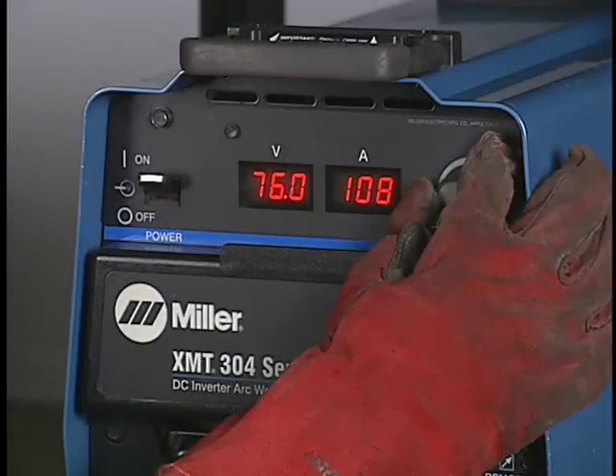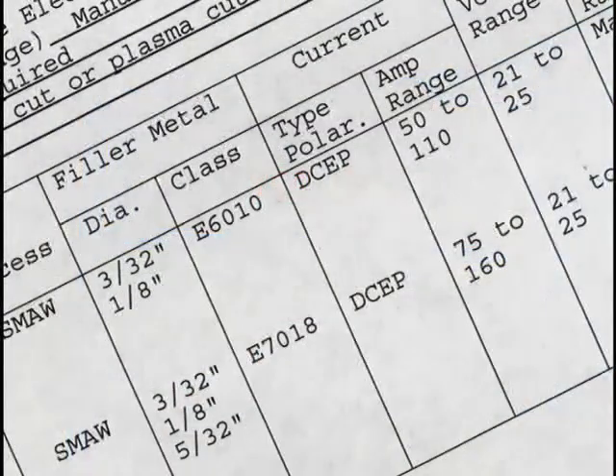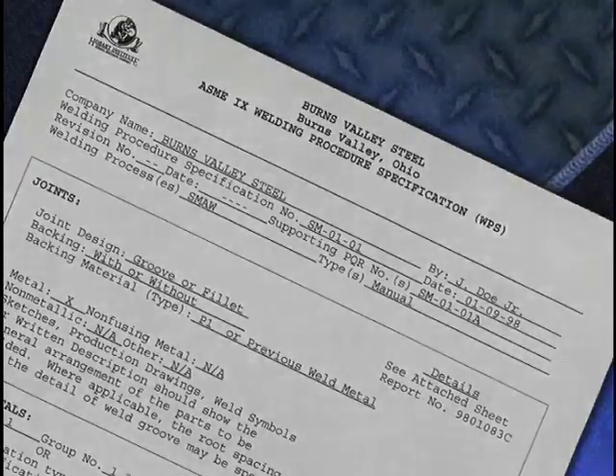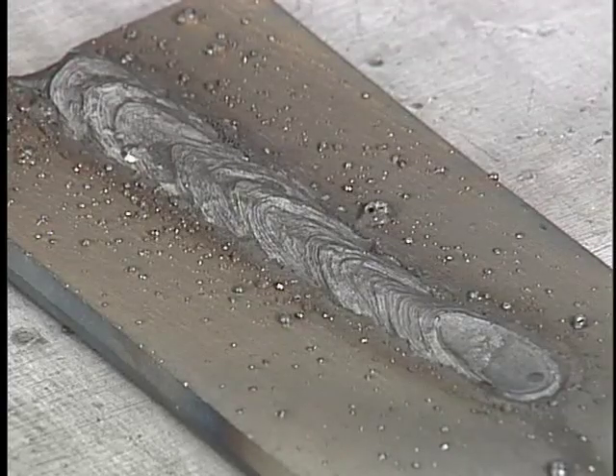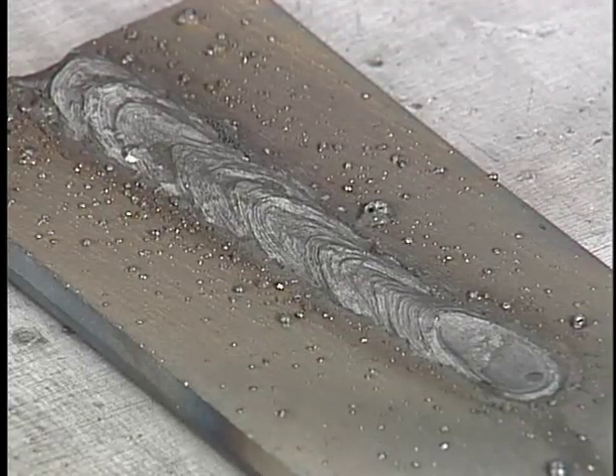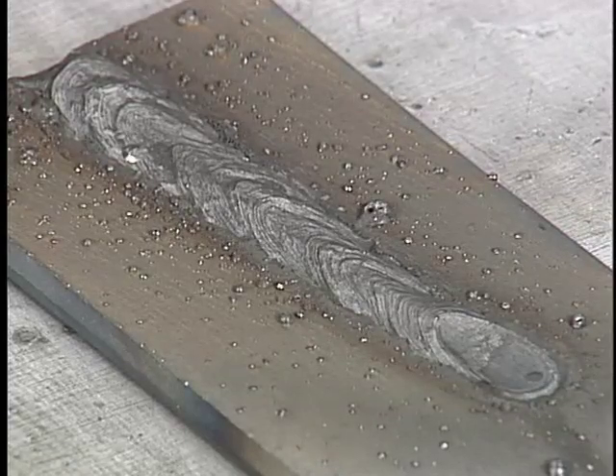Current is measured in amperes, or amps. Each type of electrode has recommended amperage ranges for optimum performance. Amperage ranges are usually specified in the welding procedure or in the manufacturer's data sheet. If the amperage is set above the suggested operating range, the electrode melts too fast. This increases deposition, and the weld puddle becomes too large to control. It could also cause the electrode coating to overheat and break down. The weld bead is wide and flat with excessive penetration and spatter, and undercutting frequently occurs along the toes.